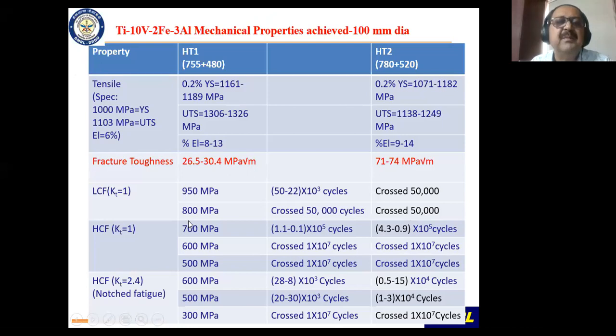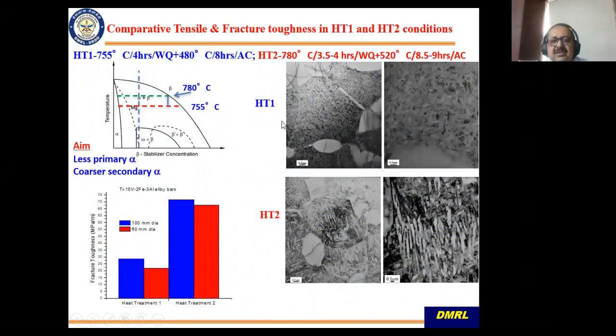These are some of the properties. You can see very high strength level, very easily achievable, but you can also get lower fracture toughness, unless you do a good microstructure control or heat treatment. But you can pump up the fracture toughness also, and then these have very good fatigue life, both LCF and HCF, and also notch fatigue life. I'm not again going into detail, just to give you a flavor I'm showing you. And again, different microstructures can give you different kinds of fracture toughnesses.